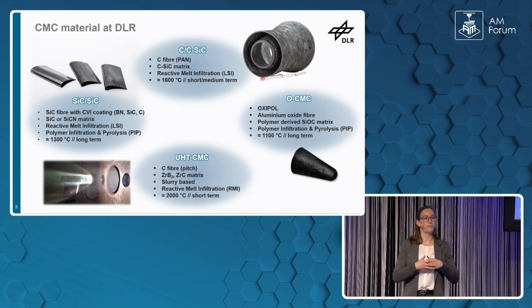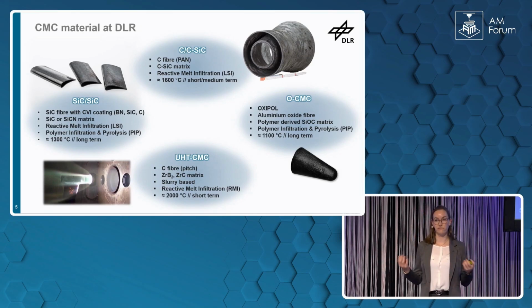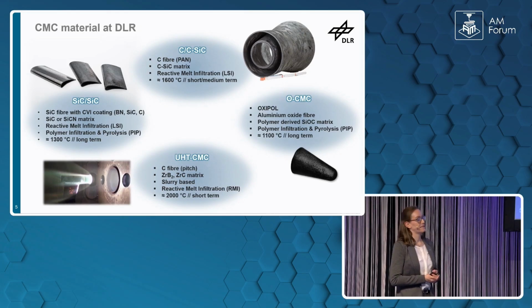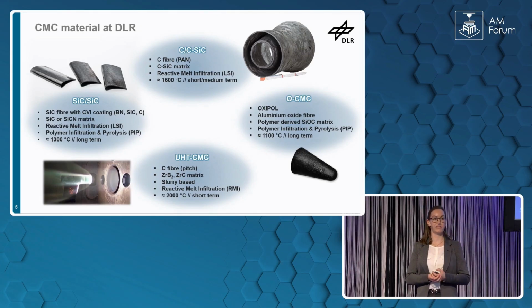All these applications require different material properties. That's why DLR has a portfolio of different CMC materials. The carbon fiber-based C/C-SiC material has a carbon silicon carbide matrix and is manufactured with the reactive melt infiltration, the so-called LSI process. High application temperatures up to 1600 degrees C are possible for short and medium-term use.